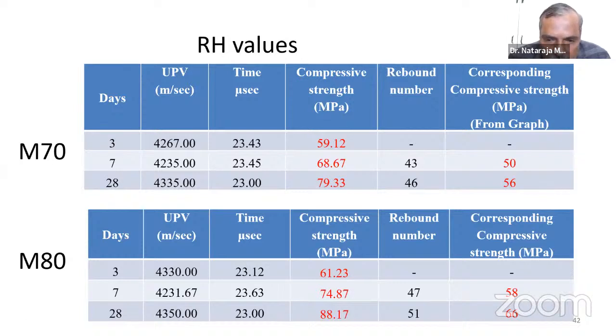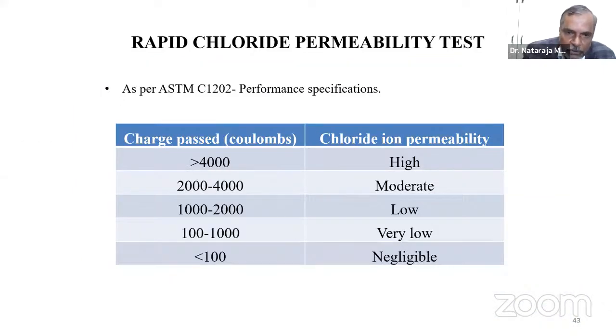The conclusion from this is your rebound hammer is valid only for standard concrete, say M20 going up to M50 grade of concrete, anything in excess of say M50. So you have to be very, very careful in interpreting the results. Your rebound hammer says that the strength is less, but your concrete strength may not be lower. So this is where the importance of certain things comes into picture. Now, rapid chloride permeability test, we got it done from the civil aid.